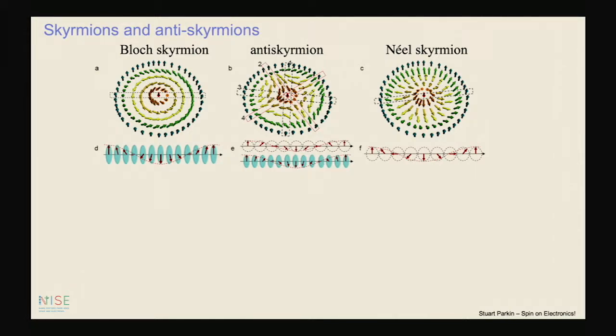It means that the Dzyaloshinskii-Moriya exchange interaction has to have certain signs and magnitudes around the circumference of this object, depending upon the crystal direction. So the anti-skyrmion structure is connected to the underlying crystal structure. So along certain crystal directions, you have Bloch walls, and along certain other directions, 45 degrees, you have the Néel walls. So we detected this anti-skyrmion using a very conventional technique, Lorentz transmission electron microscopy.